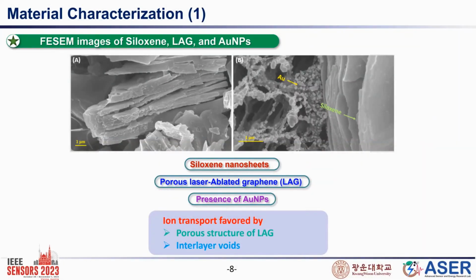It's the physical morphology of the 2D-Siloxene material we have synthesized. It shows a very good laminar structure of 2D-Siloxene, and the right one, B, shows the electrodeposited gold nanoparticles within the porous structure of the LAG, and the right one shows the individual segments of a 2D-Siloxene. So overall, I can say that the siloxene nanosheet and porous laser-ablated graphene, which is a porous structure, favor the transportation of ions from the electrolyte and the ISM also.